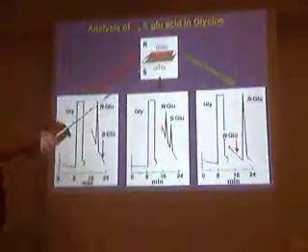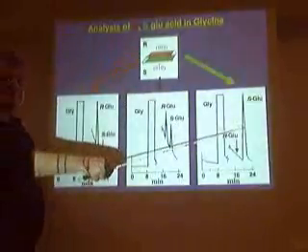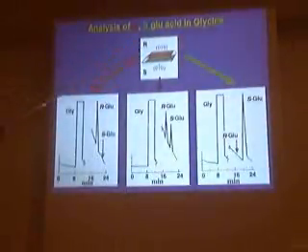And then what I say here, we are getting a spontaneous resolution of the DL amino acid within the crystals. If you grind part of this crystal, you get R-glutamic acid, S was missing. If you grind the green part, you find that the S-glutamic acid is there. And if you grind the entire crystal, you find both enantiomers in the crystal. So the next step, of course, is what happens if you grow that crystal on the interface? If you grow that crystal on the interface, you're blocking one of the faces.